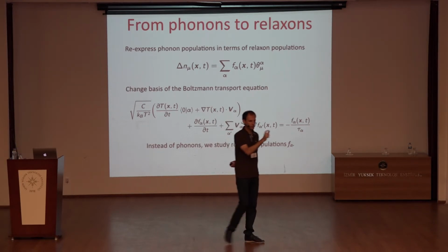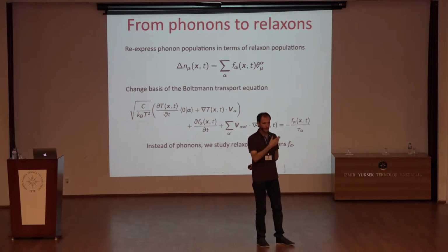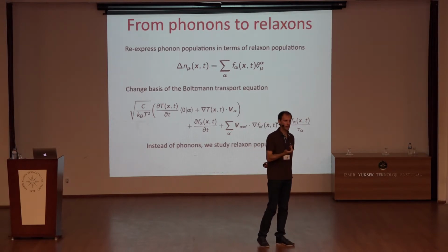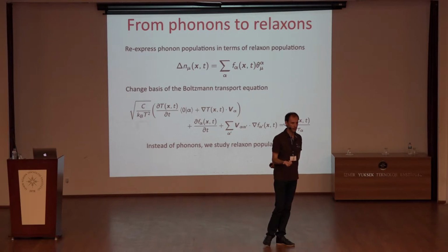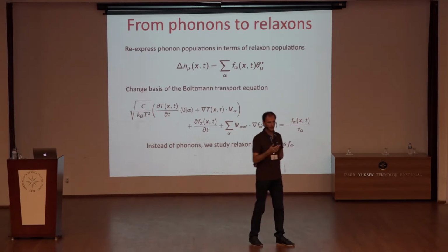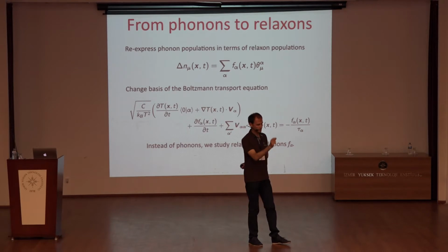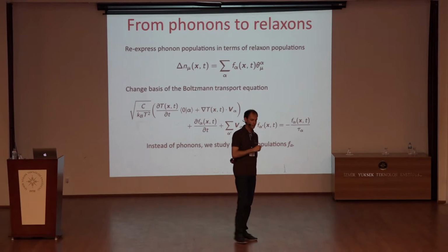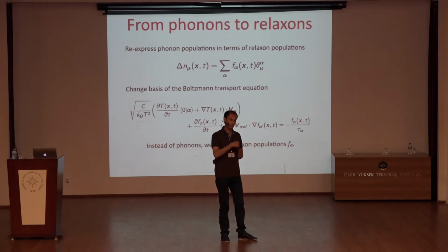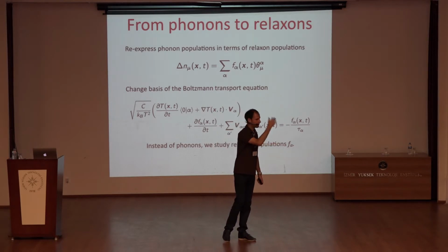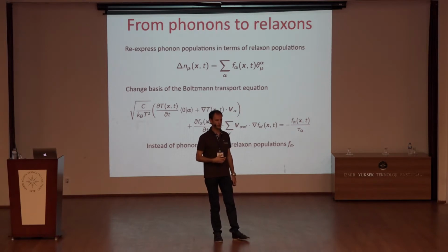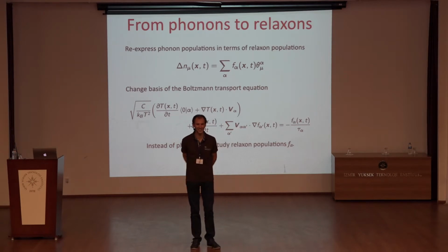But certainly, if you expect to describe things like a mean free path much shorter than the interatomic spacing, or a time-dependent evolution which happens at the femtosecond scale, for sure those are conditions that will fall outside the limits of validity of the Boltzmann transport equation, and therefore everything that I will be saying afterwards crumbles down and goes out of the limits of validity of the theory. Yeah. Thank you. You cannot have a generic theory. Yeah.